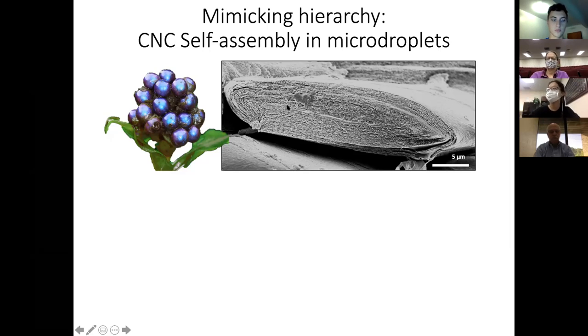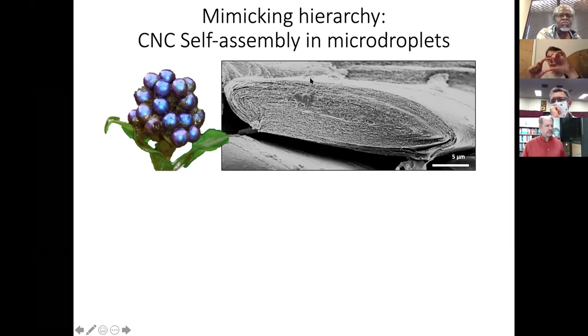This is another berry. And like the one that I was showing you before, the color is obtained by the cellulose multilayer. But the cellulose multilayer is not in a flat film, like in our case, but it is wrapped around the cell, because that's the cell wall. So since it's created inside a cell, it already has a level of hierarchy, because you have the multilayer, this helicoidal structure that has dimensionality of the order of a few hundreds of nanometers. And then this is inside a cell, which has dimensionality of the order between 20 to 80 micron. So that's what I mean by hierarchy.